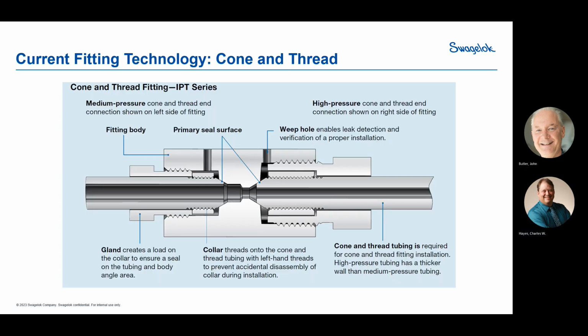One area that we can use to describe this is current technology that's out there. This fitting technology is called cone and thread. It's used very, very often on medium to high pressure systems, so pressures over 10,000 psi or 700 bar, clear up to 60,000 psi in these really high pressure applications. This fitting's been around for years and years and years. There are some misunderstandings about it in the marketplace, though.